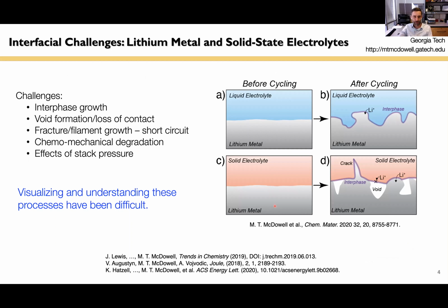So why don't we have commercialized solid state batteries already? Well, there are a lot of fundamental materials level challenges that are really quite interesting, scientifically intriguing, but unfortunately have prevented commercialization so far. And so I list some of these here. There are issues at interfaces with instabilities and interphase growth. There's contact loss of interfaces. There's filamentary growth of lithium metal to short circuit solid state batteries. Chemomechanics and the relationships between chemical changes and mechanical stress are very important in solid state batteries and can cause problems. And then also stack pressure, which I'll talk more about in this talk, plays a big role. So all of these things together are distinct mechanisms, and understanding how they interact with each other, and how they can cause degradation in solid state batteries, is really important.